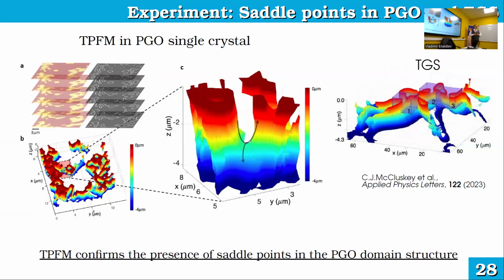But doesn't mechanically removing parts of the material renormalize the whole structure? Good question. I haven't mentioned it, but first of all, it's a bulk crystal. It's not a thin film, and bulk crystals are really more resistant to such things. But again, it's a somewhat handmade manner, and they have more rigorous statistical tools. Upon each scan and each layer removal, they gather some statistics of domain wall widths and domain wall frequency distribution, and using the statistical tools, they confirm that removing the material doesn't affect the internal structure of the domain wall. So maybe it moves plus or minus a nanometer, but you can see scales at micrometers, so it's huge actually.